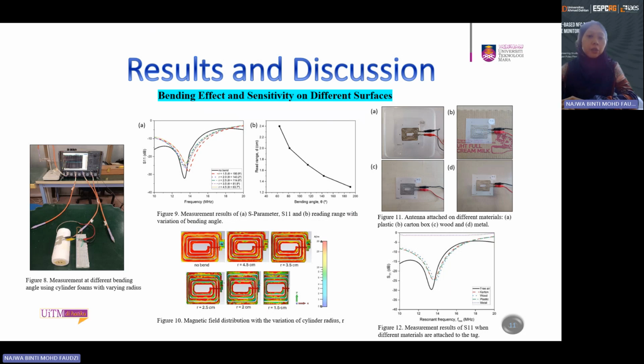The sensitivity of the tag has also been analyzed while the tag was attached to different surface materials, for example plastic, carton box, wood, and also metal. From this S11 result, we can see that the tag is not much affected when it is attached to plastic, carton box, or wood material. But when it is attached on a metal surface, the performance is significantly reduced. This is due to the existence of eddy currents on the metal surface, where current in the opposite direction is generated, which cancels out the magnetic field induced by the reader.